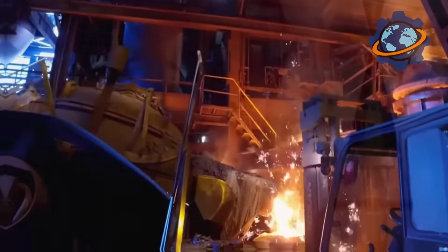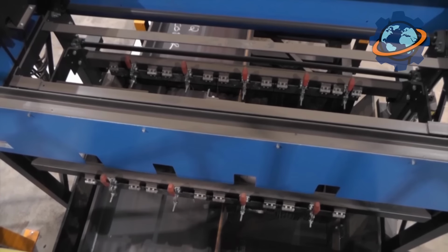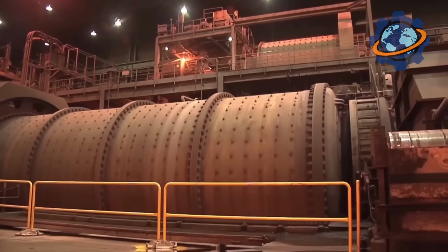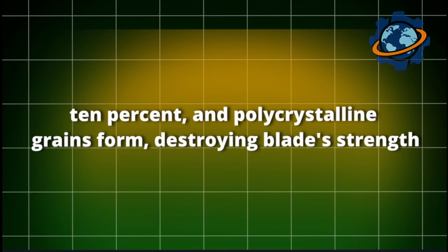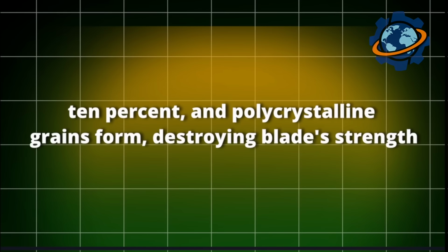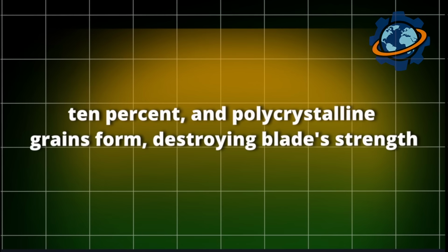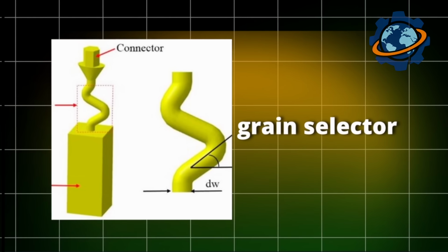This directional cooling forces crystal growth in one direction only, upward, eliminating horizontal grain boundaries where cracks normally form. The process takes 14 hours for a 4-inch blade. Rush it by even 10% and polycrystalline grains form, destroying blade strength. But here's where physics becomes art.